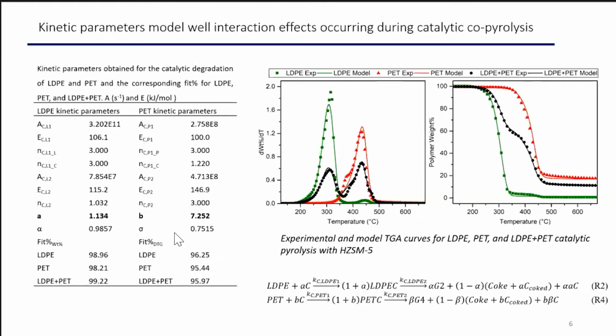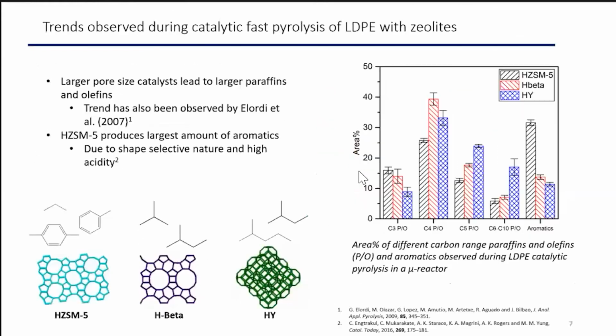So we only have one set of kinetic parameters for the LDPE and PET, and these parameters both work for the individual pyrolysis of the polymers and for the co-pyrolysis. And we were very excited to see that this reaction scheme, which had not been used before for the co-pyrolysis, was able to capture these interaction effects.